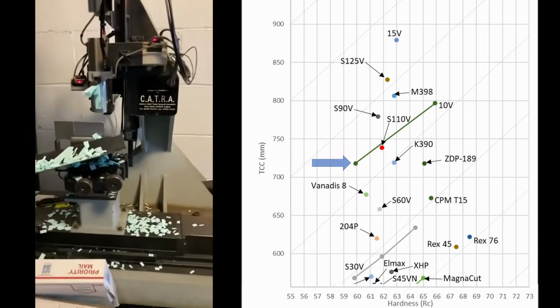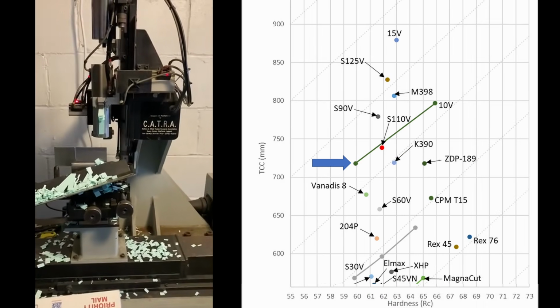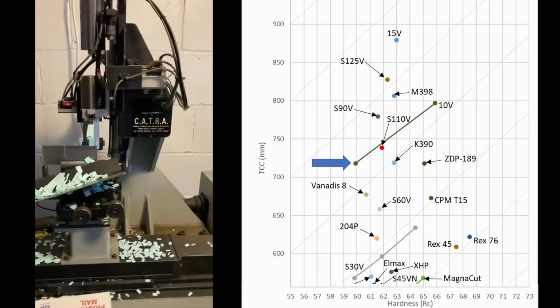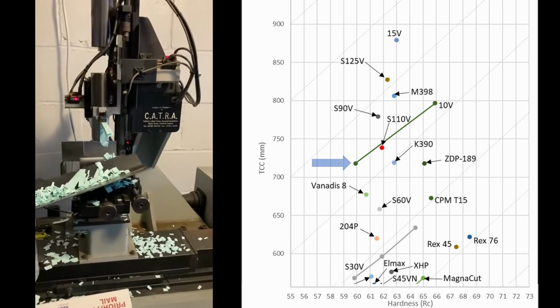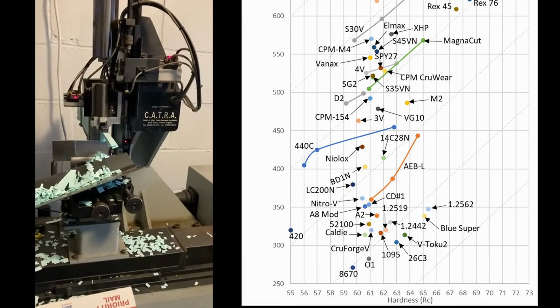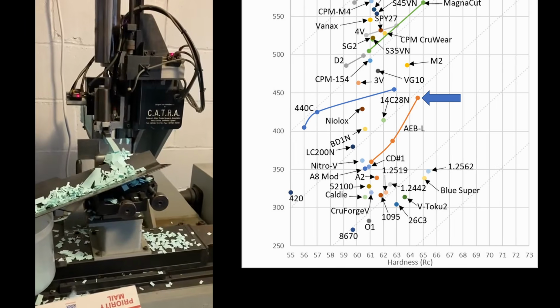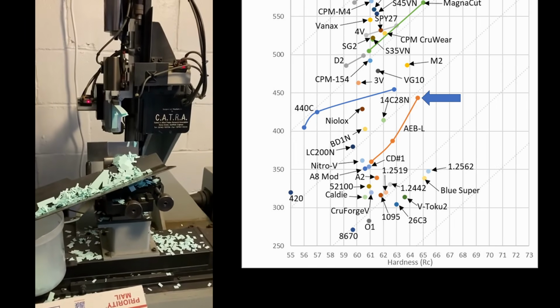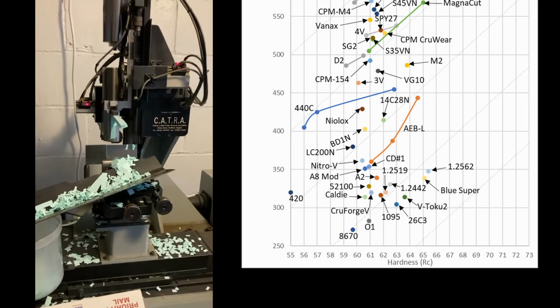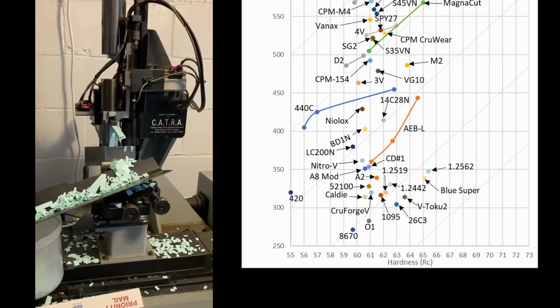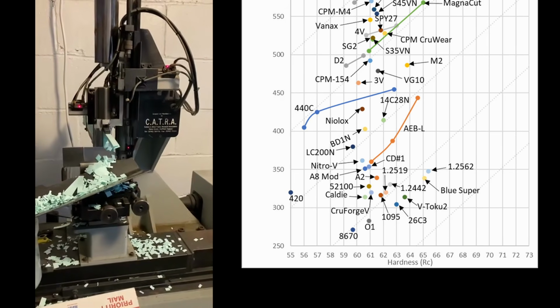You can see that 60 Rockwell C CPM 10V, a steel with about 10% vanadium and therefore a lot of vanadium carbide, has significantly better resistance to edge wear than 64 Rockwell C AEB-L, a steel with a relatively small percentage of softer chromium carbides. So better edge wear resistance is one reason for higher hardness, but is perhaps not as important as you might think.